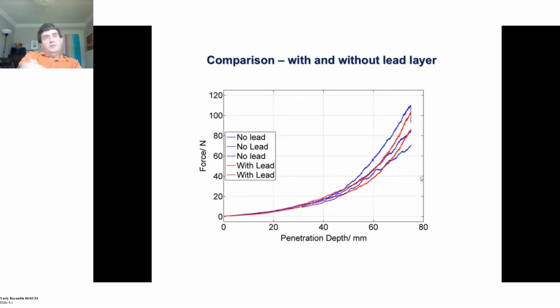One of the things you will be asked in any conference is, did the presence of the lead make any difference? And what we see here is 3 repeats showing not so much as you would notice. There is a variation of force versus penetration depth on the system, but basically up until about 40 millimeters or so, it's not very significant.